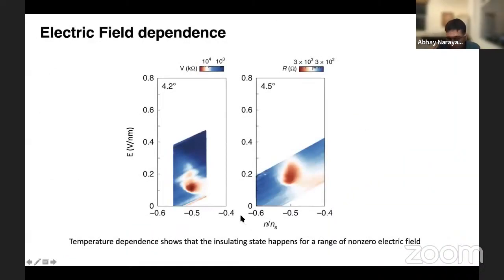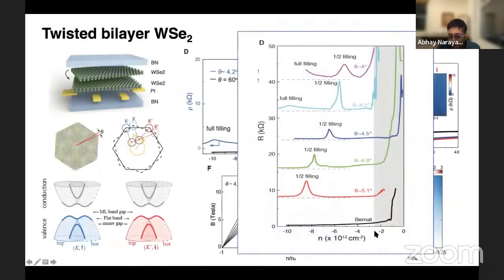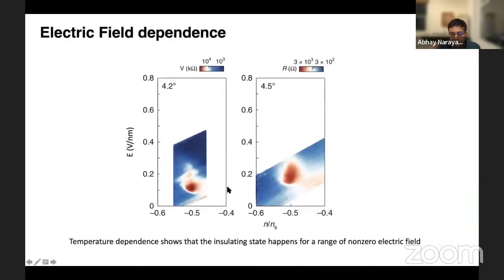Okay, so all that I've told you about so far was about what happens as a function of density. You can also ask what happens as a function of this other tuning knob that we have, which is the electric field that you can apply to the system. And if you apply electric field and density, and I can explain later if you're interested why this plot looks as funny as it does, the essential point is that there is a region of electric field and close to this half filling point where the system is an insulator. And if the electric field is too small or the electric field is too large, then the system is a metal. But for this intermediate range of electric fields, the system is an insulator. And that's schematically shown in this red elliptical region. And this is data for 2 different samples.